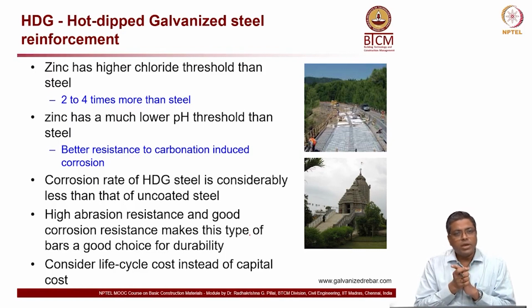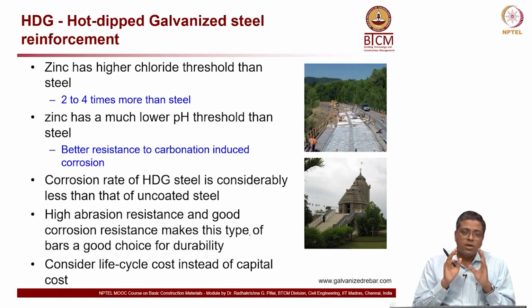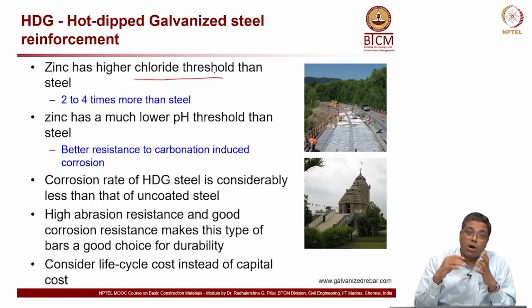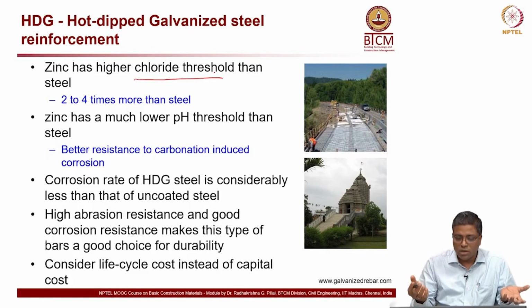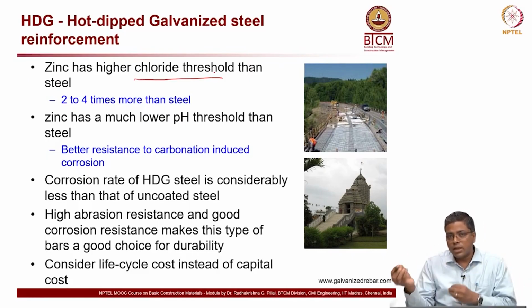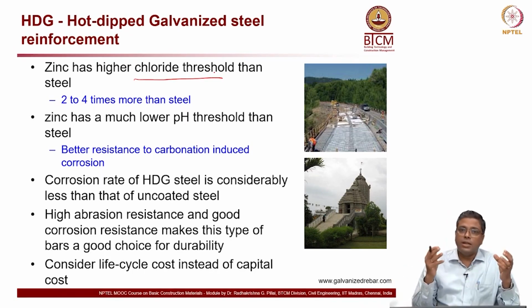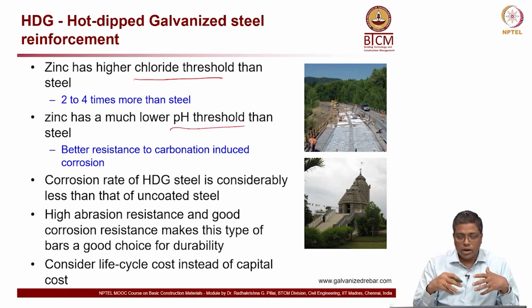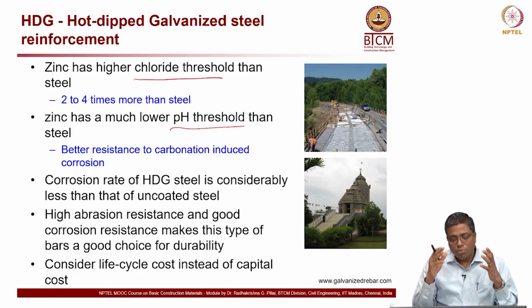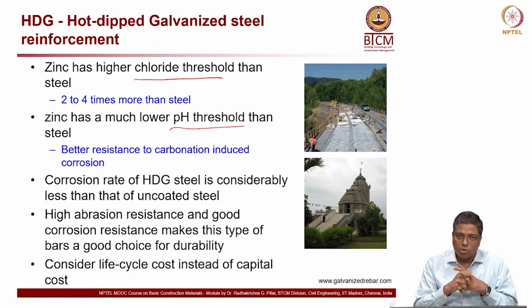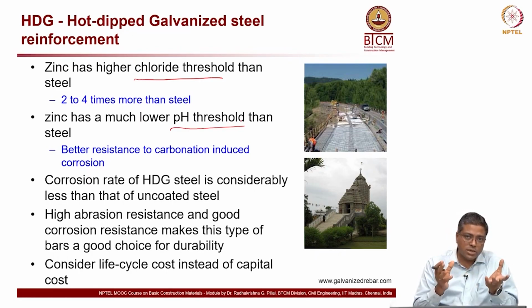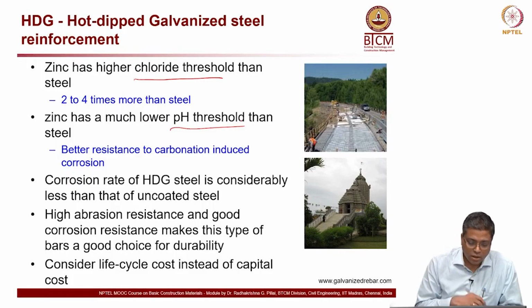I am not going into more detail. You can read about chloride induced corrosion and carbonation induced corrosion if interested, but for this class you need to remember that the amount of chloride required to initiate corrosion for galvanized steel is more than that for uncoated steel, and the amount of pH reduction required is also more for galvanized steel than uncoated steel. So in both these major corrosion mechanisms, galvanized steel performs better than uncoated steel, and also because of the high abrasion resistance, these steels are very good.